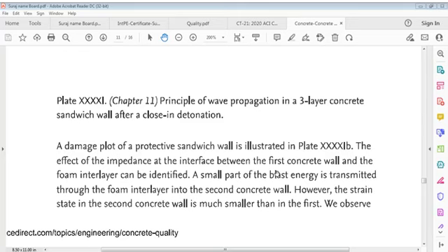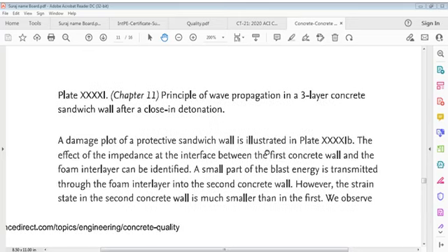A damaged plot of the protective sandwich is illustrated in this plate. The effect of impedance at the interface between the first concrete wall and the foam interlayer can be identified. A small part of the blast energy is transmitted through the foam interlayer into the second concrete wall. However, the strain state in the second concrete wall is much smaller than in the first.